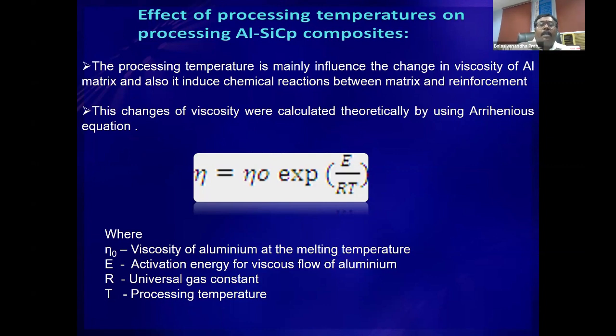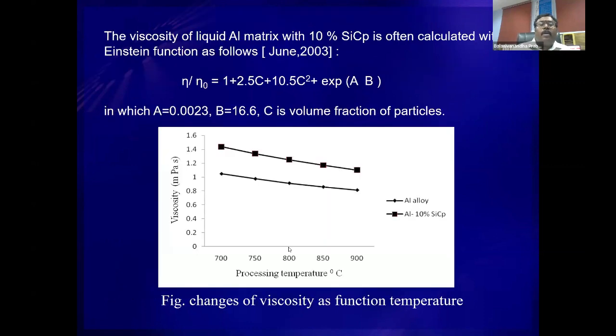So one controlling parameter in this process is the temperature. The temperature may play a major role in controlling your particle distribution. Here you have data which we have calculated: for the aluminum alloy, the viscosity drastically reduces from the melt temperature to 900, but when I add 10% silicon carbide particles, the viscosity is still very high. So that means it is a highly viscous medium, and distribution is very, very challenging.